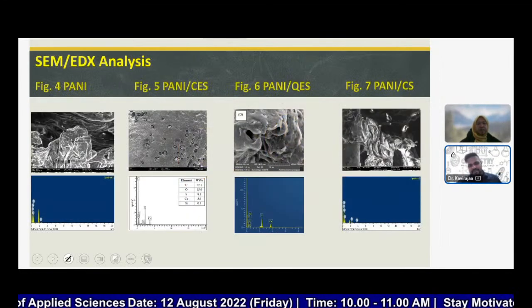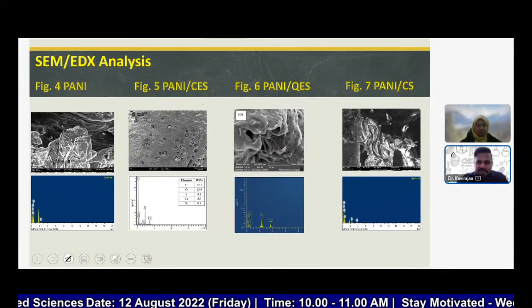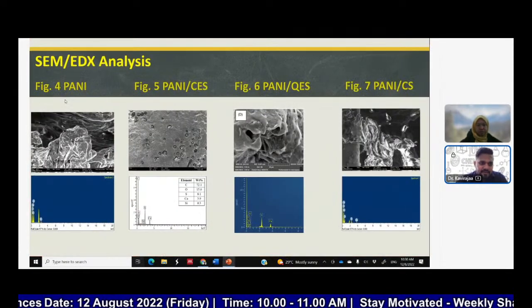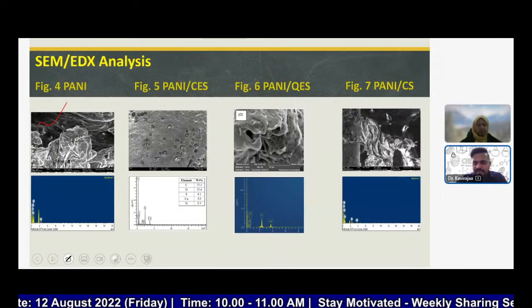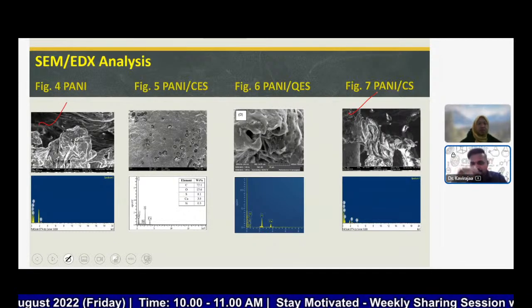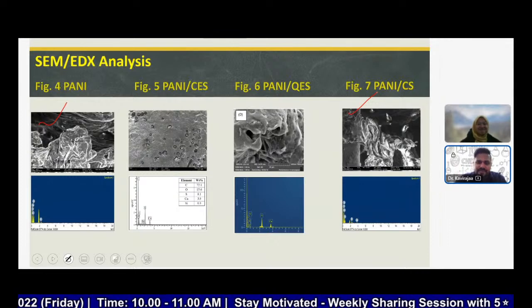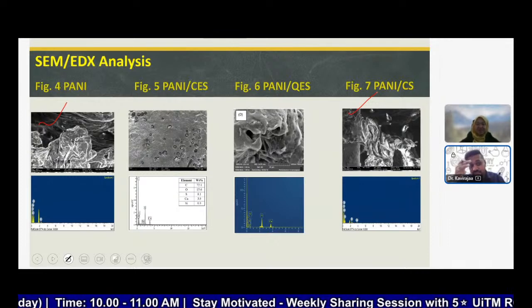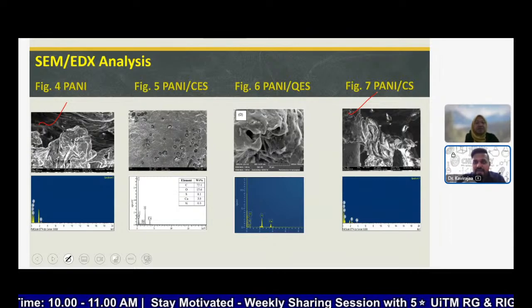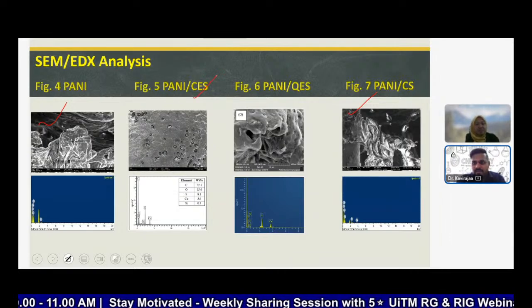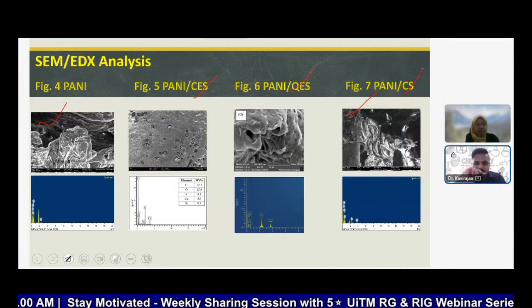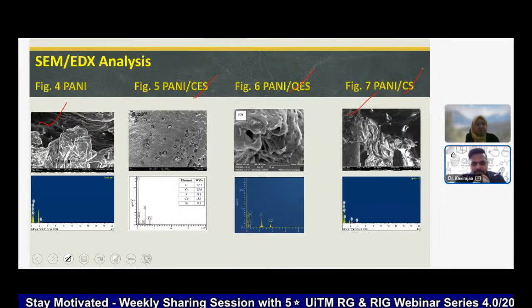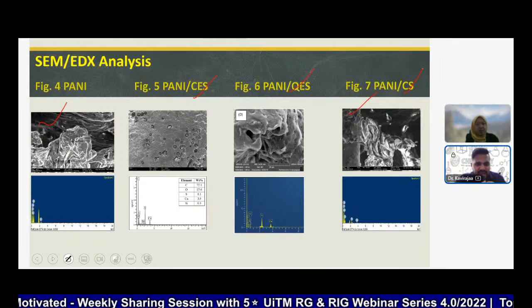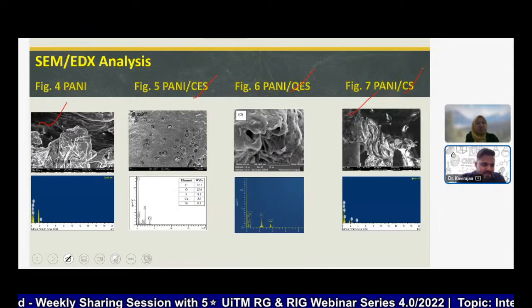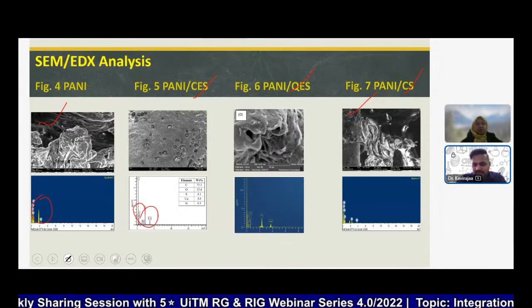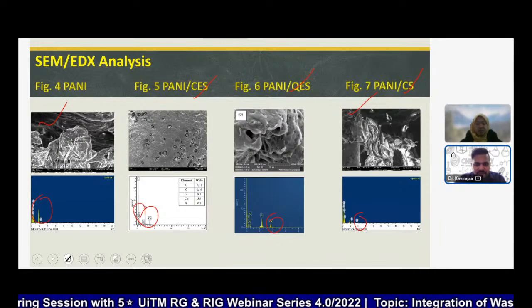Okay, so this is some of the EDX analysis. Actually, this EDX and this EDX are from the same instrument, because as time goes by, I furthered the study with a different batch of FYP students. So first we studied the chicken eggshells, then we studied the quail eggshell, then crab shells. We actually wanted to make sure that we can find the calcium through the EDX. So in all EDX spectra, we can find the calcium. So it has been well blended.